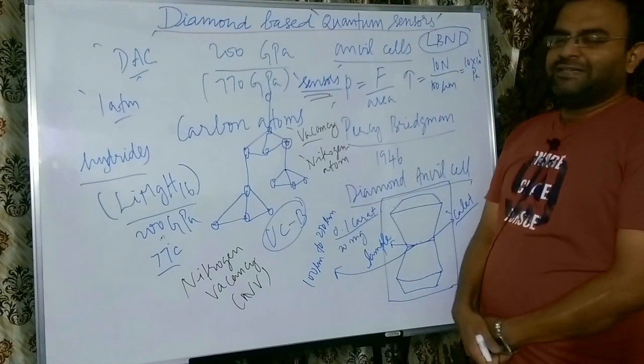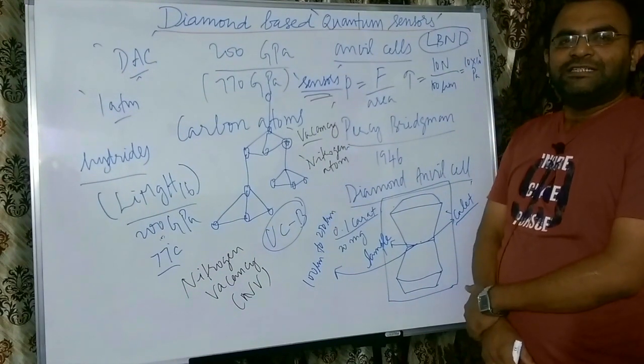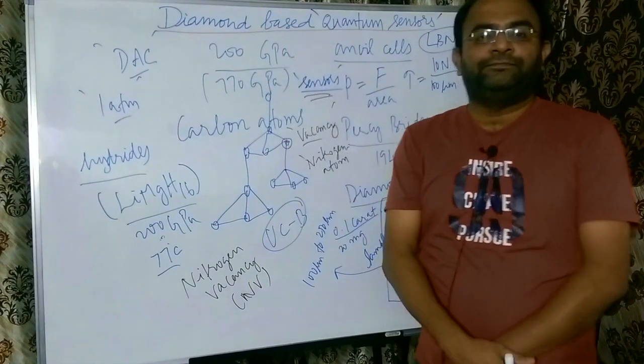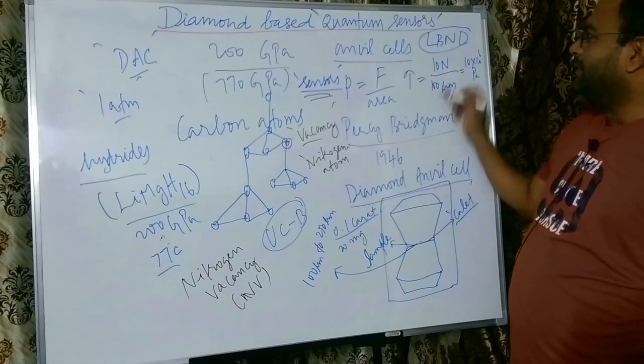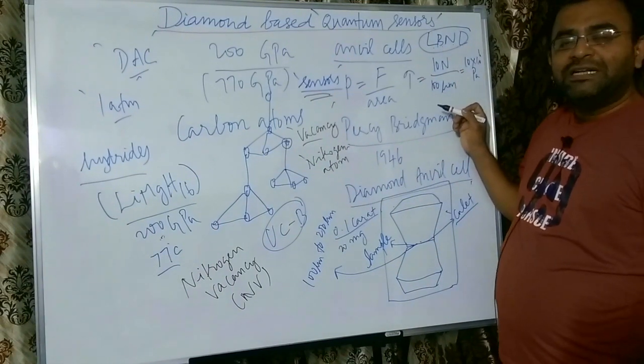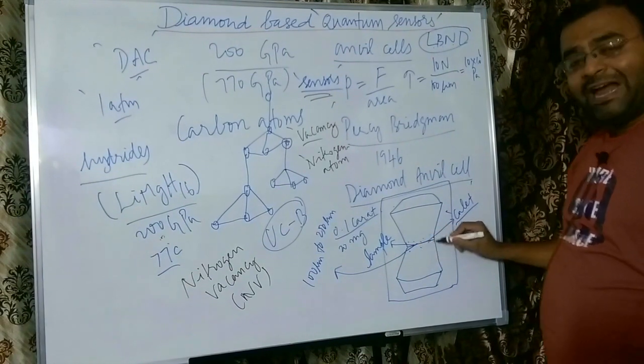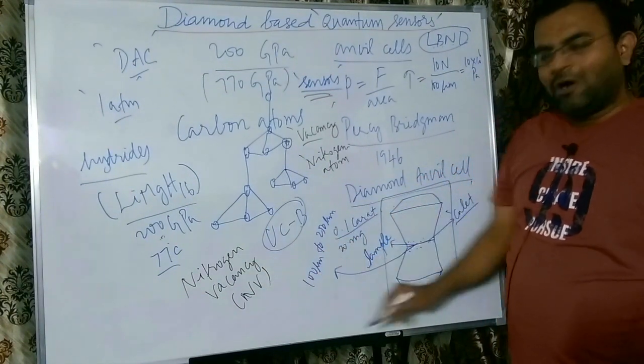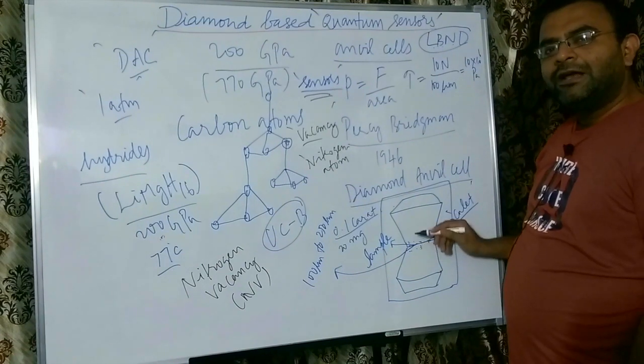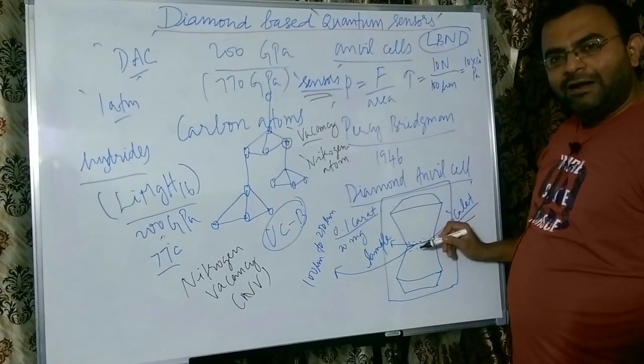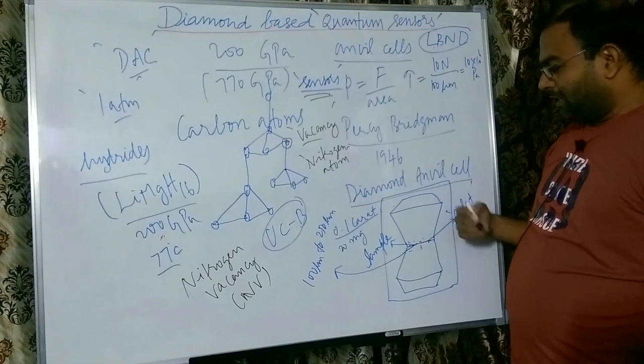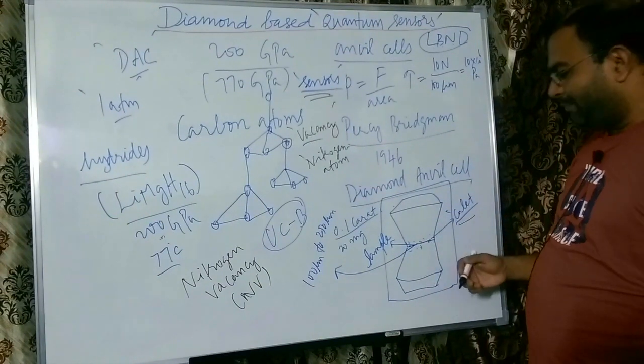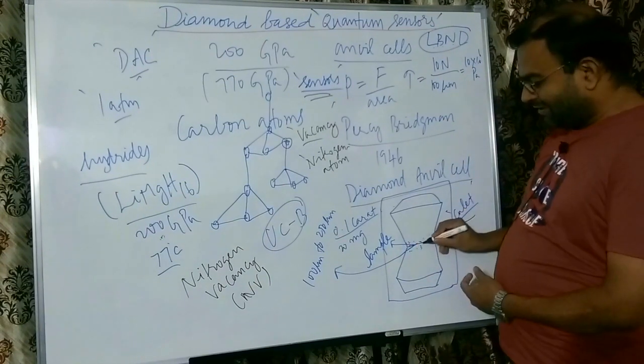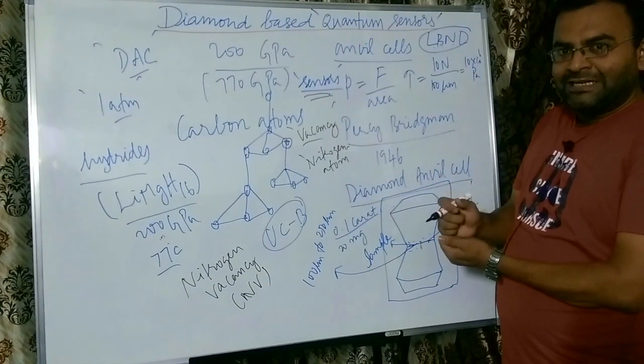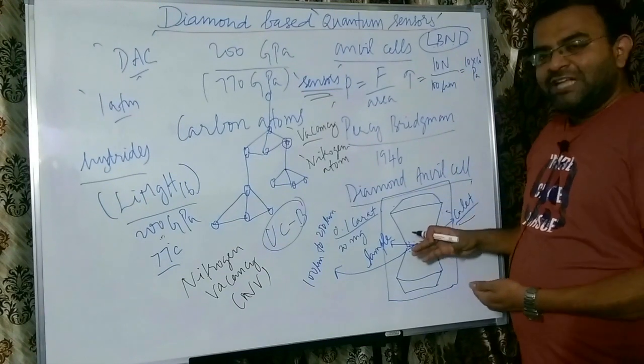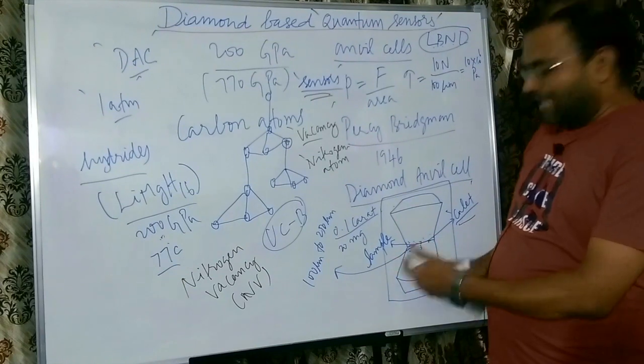Therefore, in these quantum-based sensors, it is possible to study changes in extreme conditions using diamond, so we don't have to have a separate sensor. The group at Lawrence Berkeley National Laboratory engineered the material in such a way that these naturally occurring nitrogen vacancies are artificially created a few layers thick on either side of the anvil cell culet, and these nitrogen vacancies automatically sense any property that is changing. For example, if the structure of a material placed here and compressed at extreme pressures varies, that structural change can be converted into a change in the luminosity of the fluorescent light emitted from this region.